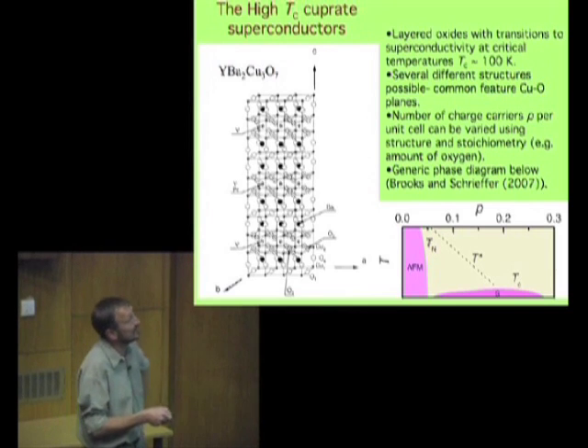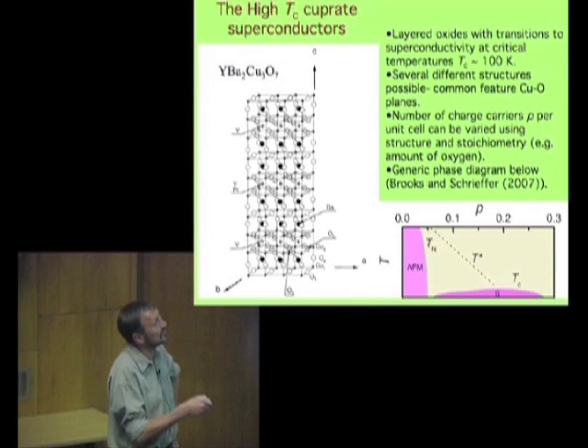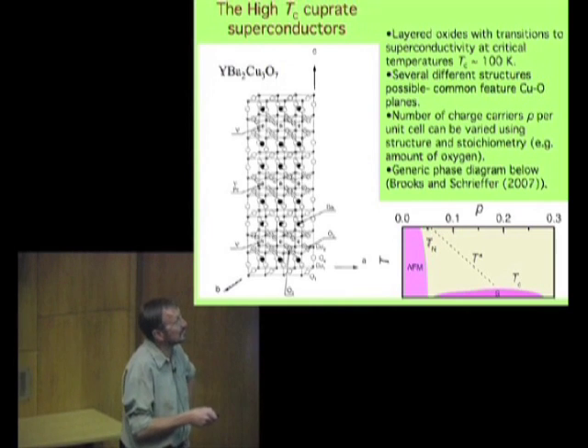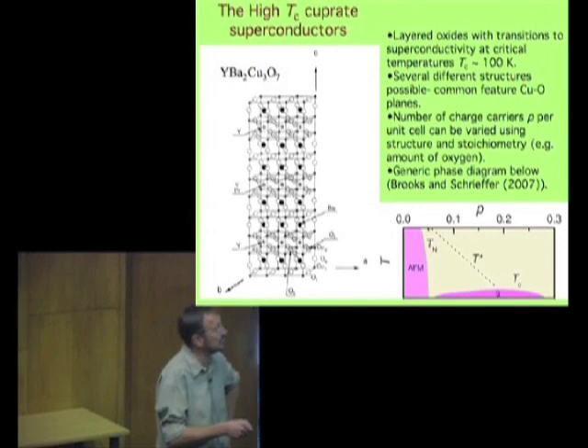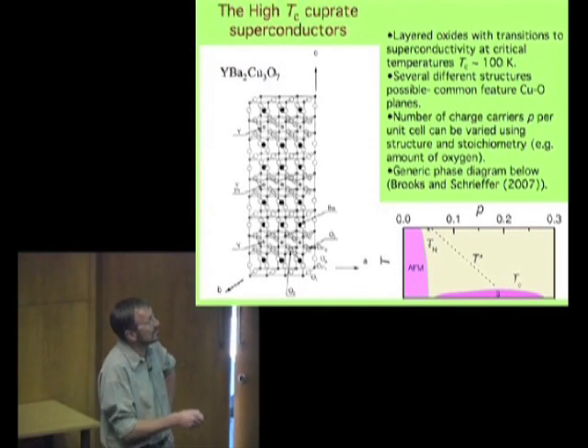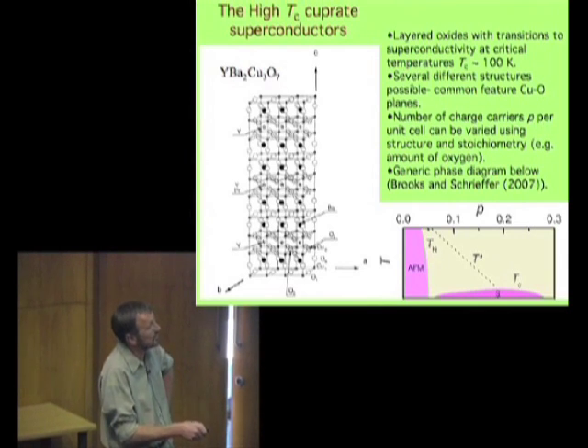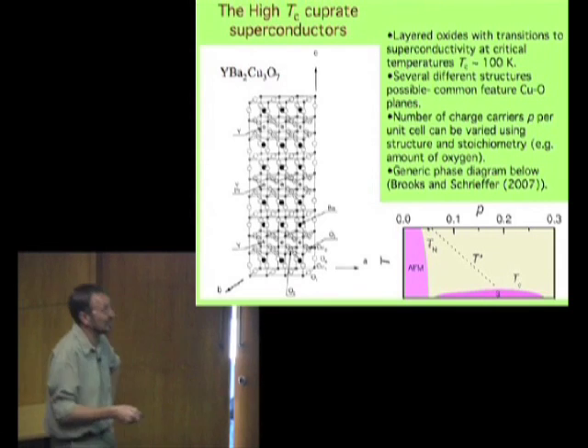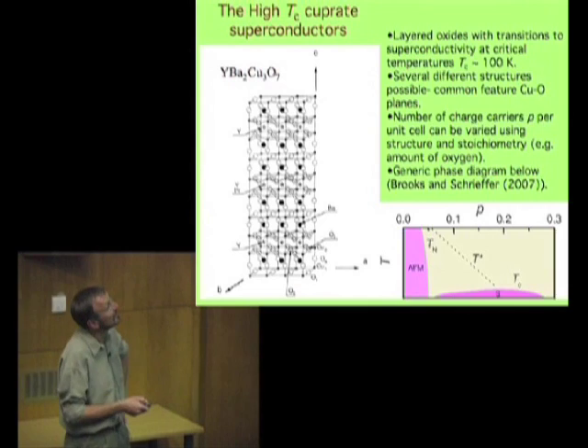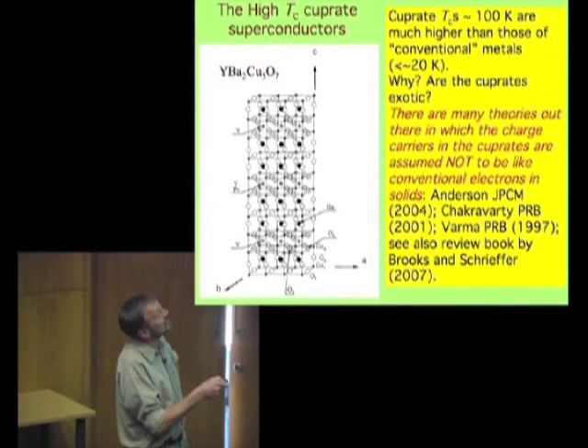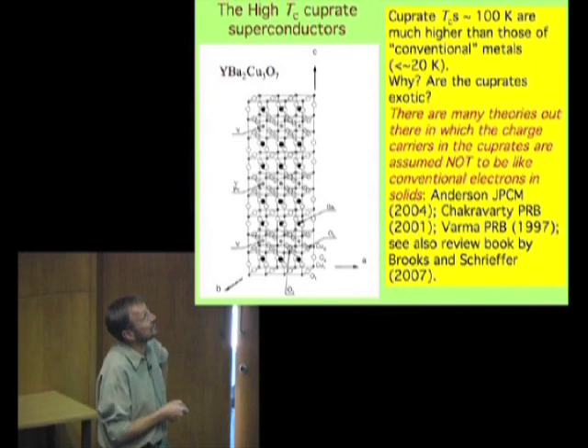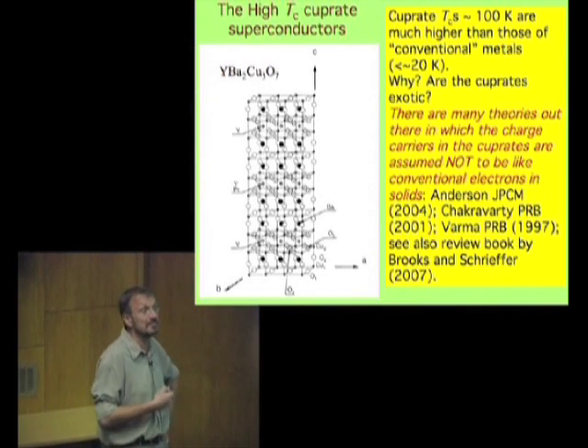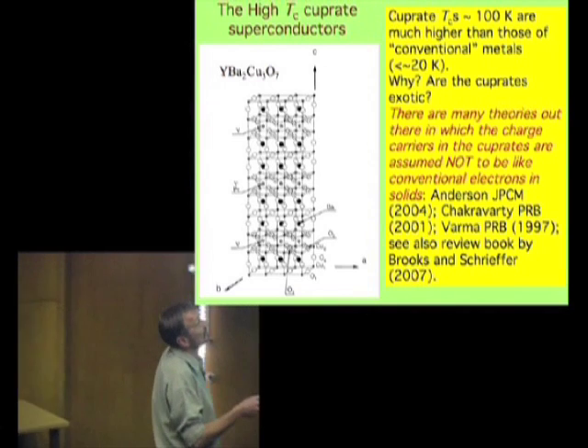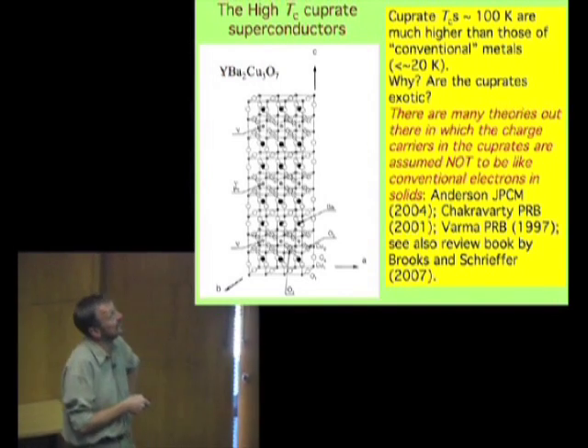This is a very simplified generic phase diagram of these things from Brooks and Schrieffer's recent textbook. Basically, this is temperature with absolute zero at the bottom. This is hole doping, hole concentration per unit cell. We have antiferromagnetism down at low numbers of holes. And then finally, as we increase the number of holes, we get this superconducting region here, with the top of this dome being something like 100 Kelvin. So these critical temperatures for superconductivity, of around 100 Kelvin, are much higher than those of conventional metals, which tend to be restricted to less than 20 Kelvin.